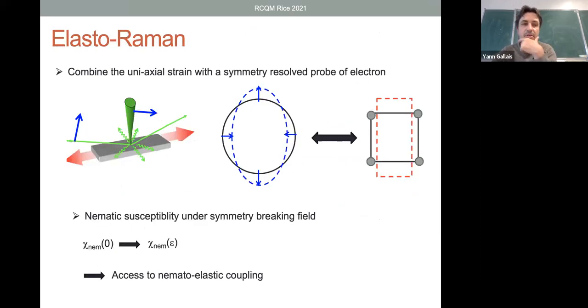Let me just very briefly show you that one way to address this problem is to do elasto-Raman. We recently built a setup combining symmetry-resolved Raman scattering with uniaxial strain. This allows us, in the specific case of the nematic, to probe the nematic susceptibility under a symmetry-breaking field.